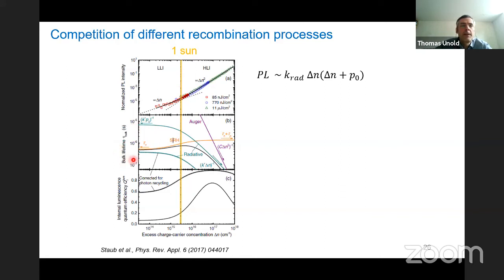Now, if you look at the lifetime, it gets more complicated. You have these different contributions. This green curve is the radiative lifetime. It always gets smaller the more carriers you have. Auger also goes by N to the cube. And then the Shockley-Read-Hall lifetime is even more complicated because it goes from being limited by, under smaller injection conditions, for instance the electron capture lifetime, to the sum of electron and hole lifetimes. And then if you add these all up, you get the black curve. So you can see it first stays constant and increases slightly and then it decreases strongly with excitation.